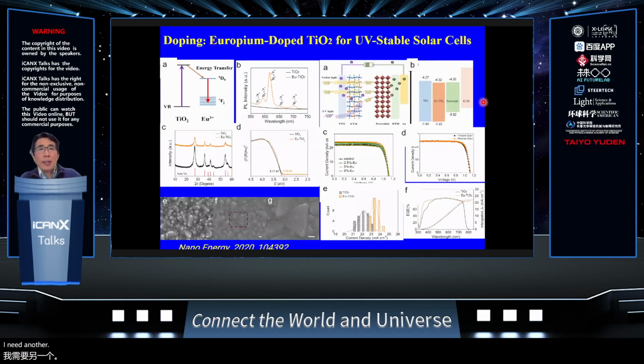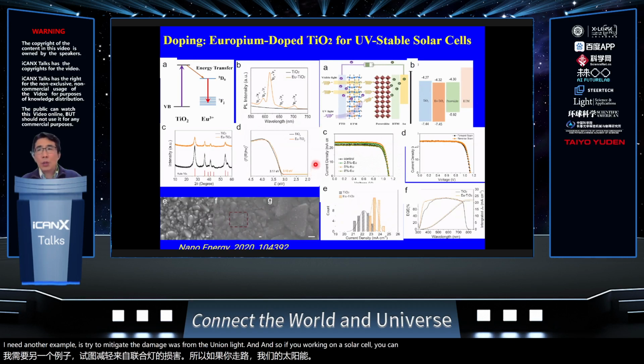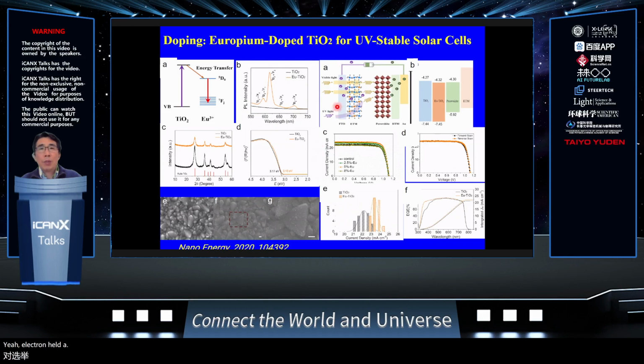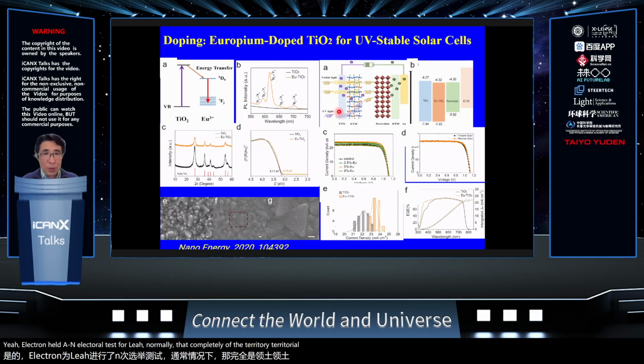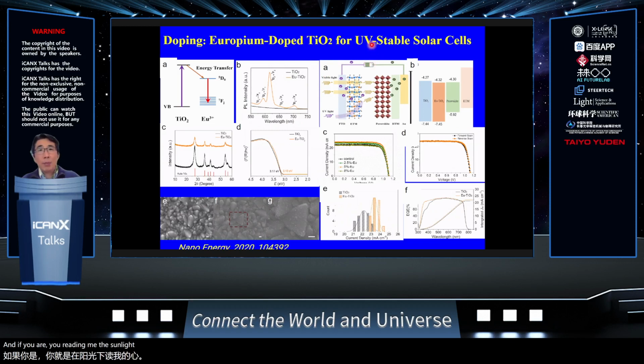Another example is to try to mitigate the damage from UV light. If you're working on solar cells, you will know the electron transport layer is normally a compact layer of TiO2. TiO2 itself is a photoactive material, and if you irradiate with sunlight, there will certainly be UV light. This UV light has high energy, which can damage the perovskite, because of the photoactive function of the TiO2.